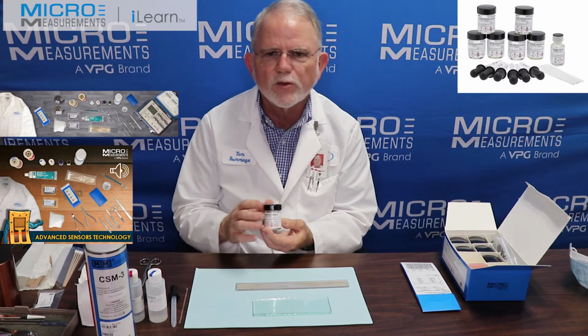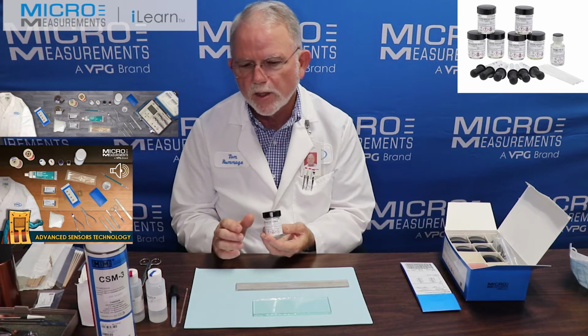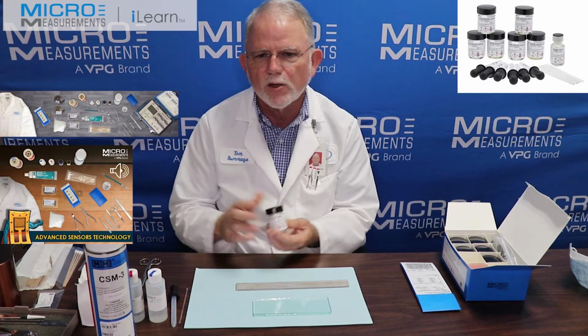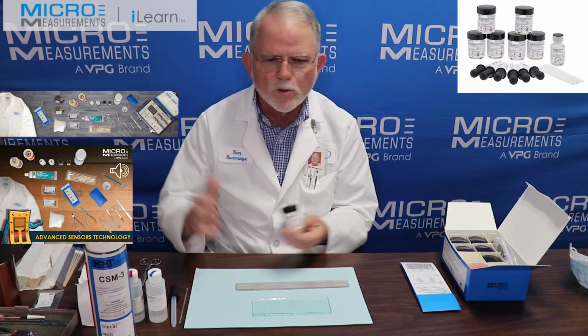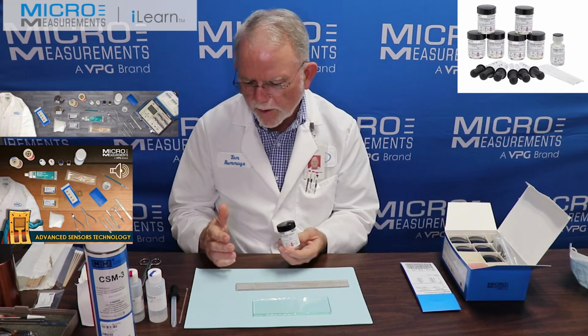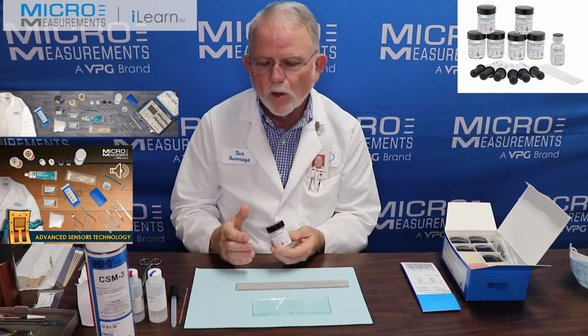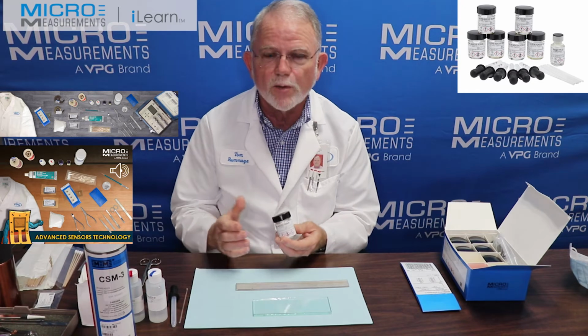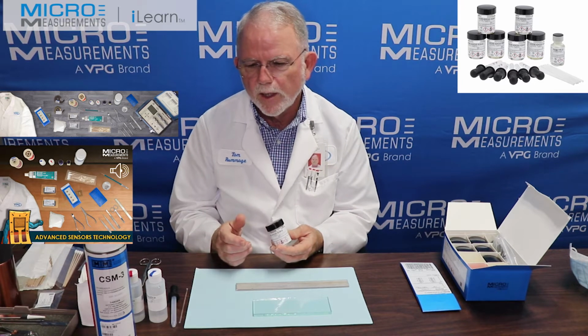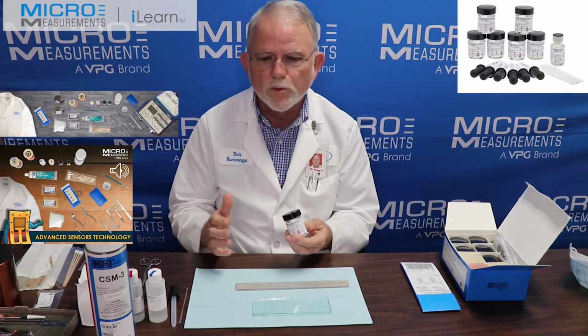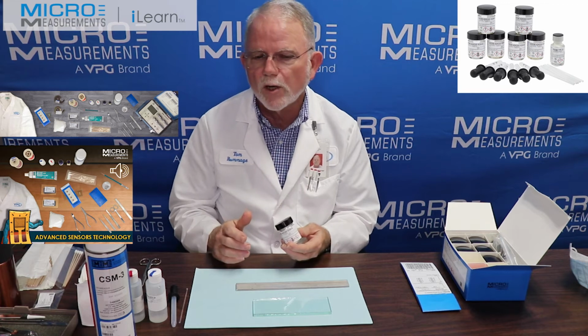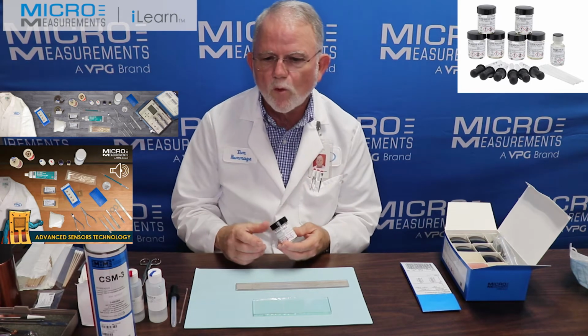For the last 10 or 15 years, our customers have been asking us, why is it we don't rate our AE-10 or our AE-15 to higher temperatures? We use it all the time and it seems to be fine. Well, about 6 months ago, we began an exhaustive study into that particular aspect of AE-10. And we've discovered that it can go upwards of 400 degrees Fahrenheit with relatively good performance.